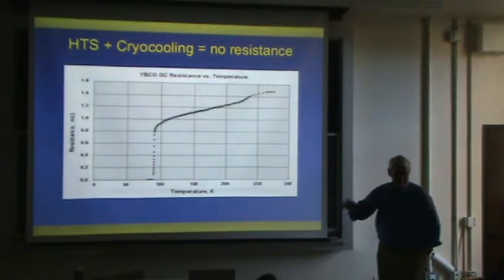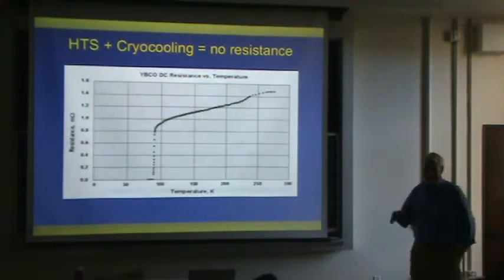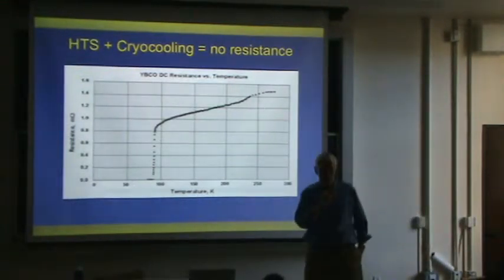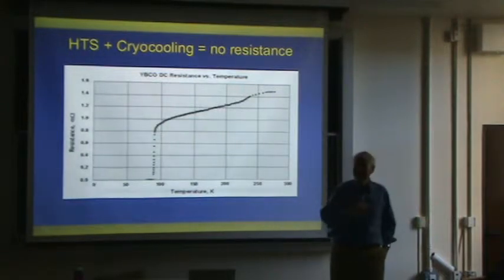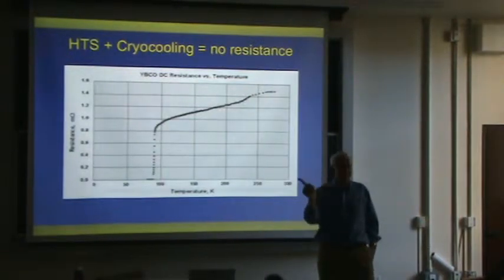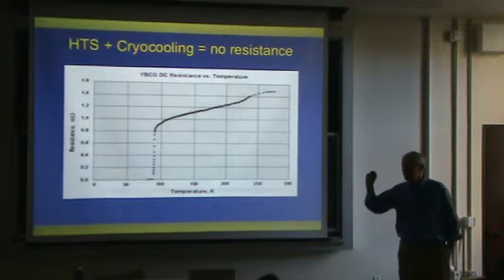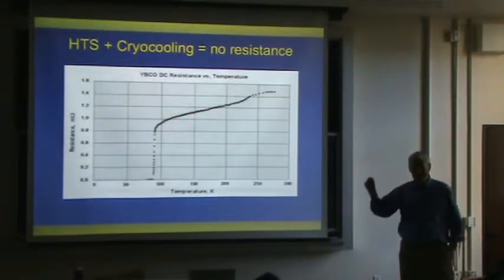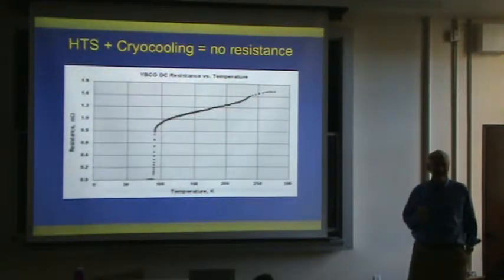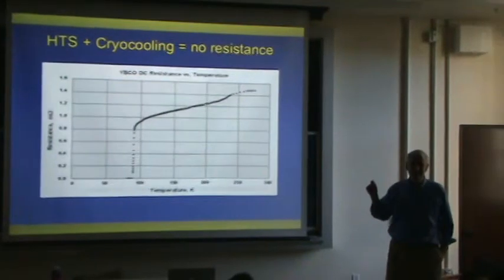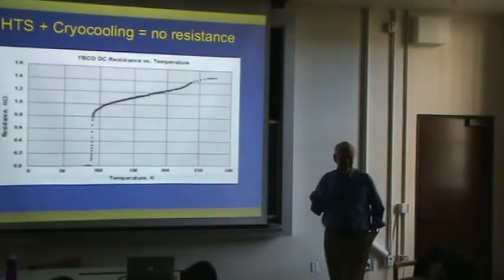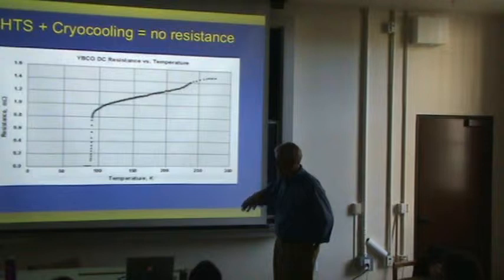So they therefore did the same recipe as Bednorz had worked out. And although I didn't tell you when they decided to publish, I'll come back in a minute. They took the same recipe, but they replaced lanthanum by yttrium. And then the same thing happened again, which is they got a completely different material, not the one we're trying to make, whose structure I'll come back to.